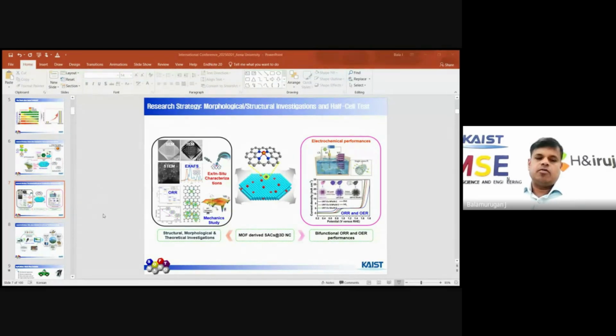With the DFT calculations, we also predict the optimal catalyst, because if it is close to the zero Fermi level, then it may be more active towards ORR or OER. And we also do the theoretical test before doing the device performances. We have to check the oxygen reduction performance by theoretical testing. For the reference electrode, we usually choose based on the electrolyte. Acidic means we have to use silver chloride, but basic means we have to use mercury oxide, HgO. The counter electrode is usually a carbon rod instead of platinum, because platinum may be corroded during the electrochemical performance. The working electrode should be our electrode, maybe coated over carbon paper or whatever substrate, like a current collector.